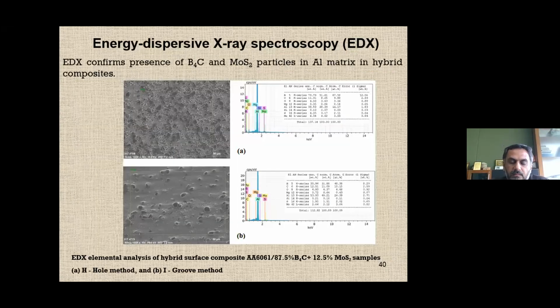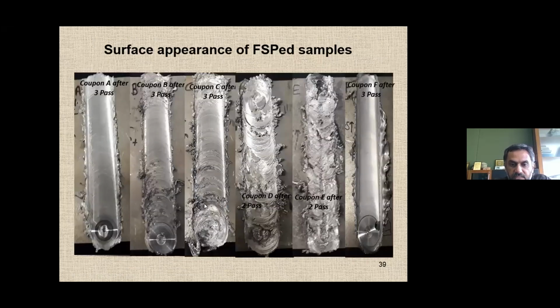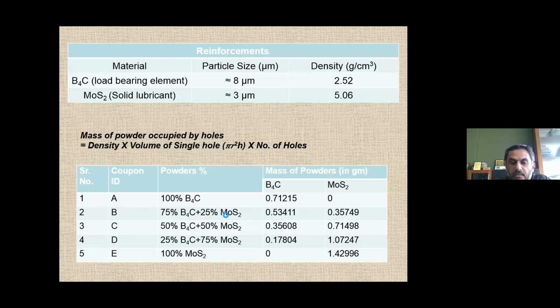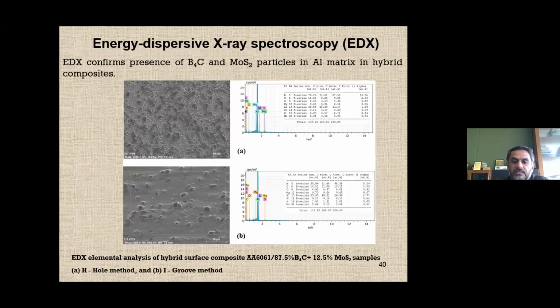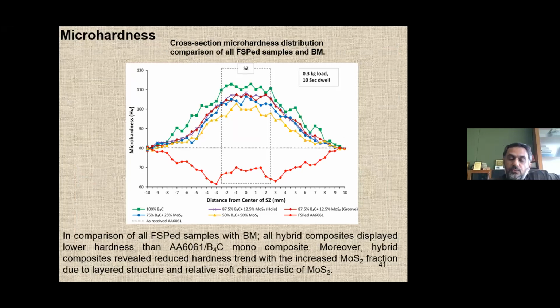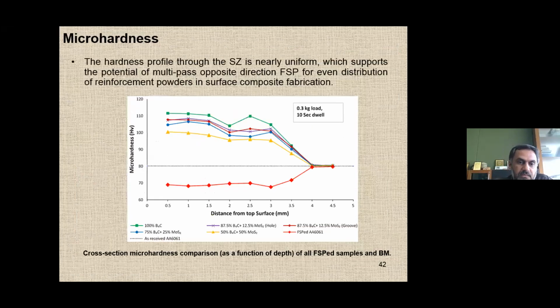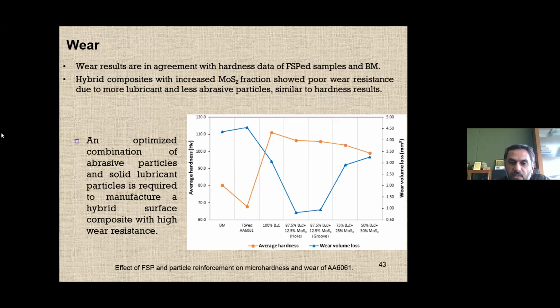And you see the energy-dispersive X-ray spectroscopy (EDX) was done, and it confirms the presence of MoS2, and it also confirms the presence of B4C in the matrix of aluminum. And after going for the wear behavior, we found that this particular one, which has the 25% MoS2, has very good wear resistance, and that subsequently helped us to characterize the wear behavior. So that motivates us to do further reduction, because when we did the wear testing, we found that the 25%, yeah, let me show you, yeah, you see here the wear behavior.